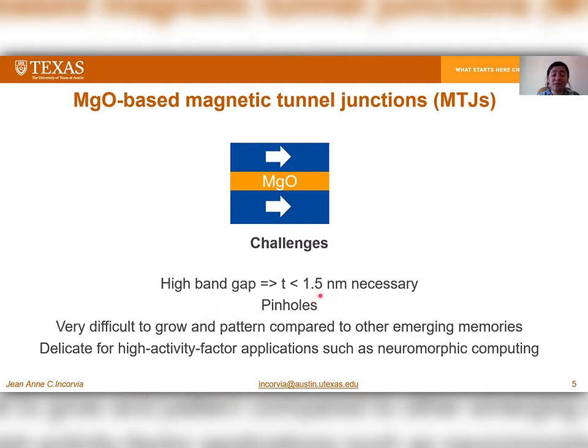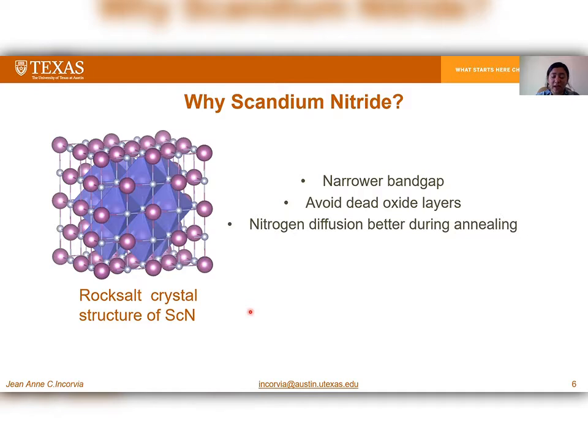When the thickness is less than 1.5 nanometers, there are a lot of pinholes in these barrier regions. Also, MgO is transparent in nature, and with the limitation of a very thin barrier region, it's very hard to grow and pattern these compared to other emerging memories. Therefore, it's delicate for high activity factor applications such as neuromorphic computing. These challenges and limitations of MgO are what led to the exploration of scandium nitride.